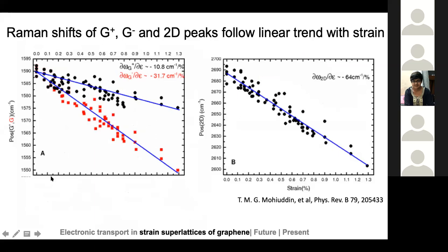So the x-axis, which has somehow disappeared for this curve on the left, both of them are supposed to have the same axis. I'm sorry about that. But the x-axis shows you the strain and the y-axis gives you the shift in the Raman peak. You'll see that all of them have a linear variation. And so if you can somehow estimate what the Raman shift is going to be for a certain known amount of strain, you can calibrate what the strain is going to be for different Raman shifts. In fact, there is something called Gruneisen parameters, which I won't speak about, which are characteristic to your materials, which give you the slope of this curve. And you can also use those Gruneisen parameters for going from the Raman peak shift to the strain.